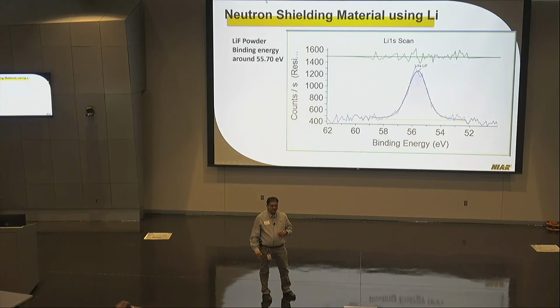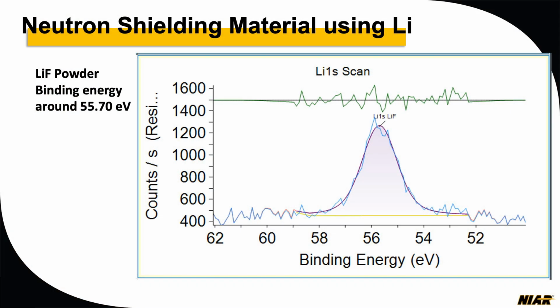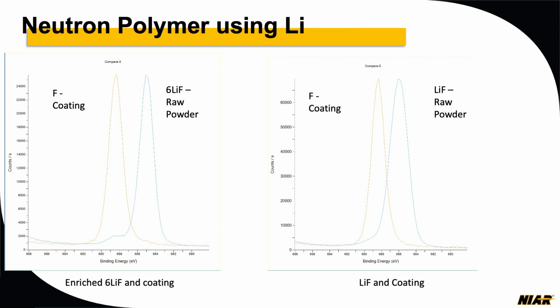So this sample was a little bit difficult to work with because of the lithium aspect of it. We definitely had initial test parameters of a lithium fluoride that has been provided. These are basically two different graphs, one with an enriched lithium and coating system, and another graph with a standard lithium fluoride and coating system. The blue graph on the right shows the lithium powder as an initial reference that we have used, and your fluorine component that basically pops up.